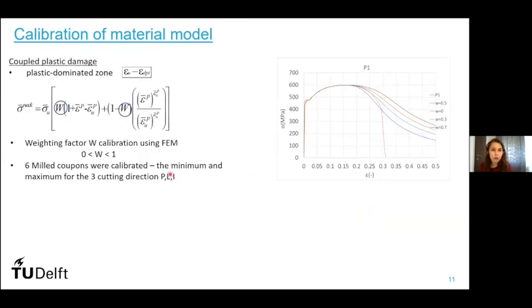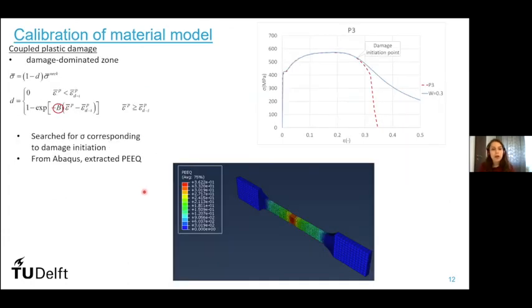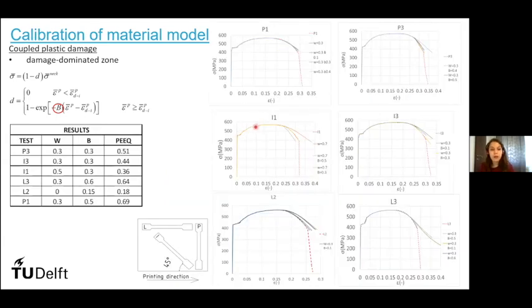I calibrated the damage parameters for 6 coupons, which were the minimum and the maximum for the 3 cutting directions: perpendicular, longitudinal, and inclined, with the weight factor taking values between 0 and 1. After finding the suitable weighting factor for all the tests, I looked for the damage initiation point, searched for the corresponding stress for damage initiation, and from Abaqus, I extracted the plastic equivalent strain. In the end, I calibrated the damage parameters for all 6 coupons that I analyzed, the maximum and minimum of every cutting direction from the plate.